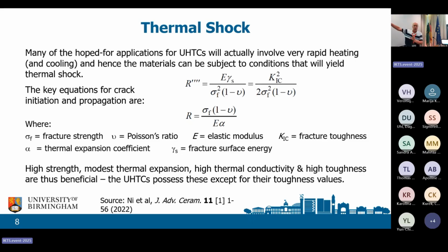And cutting to the chase, the important things are things like fracture strength, Poisson's ratio, elastic modulus, the toughness, of course, thermal expansion coefficient, and fracture surface energy. Although that fracture surface energy doesn't tend to vary very much. So a high strength is obviously good. A modest thermal expansion is good, but then it's less good for bonding to metals. A high thermal conductivity we know is good. It spreads the heat. And a high toughness. And UHTCs have these properties, except the toughness. Toughnesses are very, very limited.